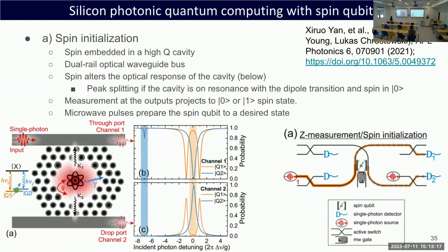Yep. So you have your detectors in the fridge, the qubit out of the fridge. That's interesting. That would certainly make things a little bit easier. Realistically, what would fundamentally limit this is probably that free carriers at room temperature are going to massively screw up the qubits. But maybe 77 Kelvin or 20 Kelvin, and 20 Kelvin is pretty easy to work at. Sounds warm. Yeah, it's very warm.